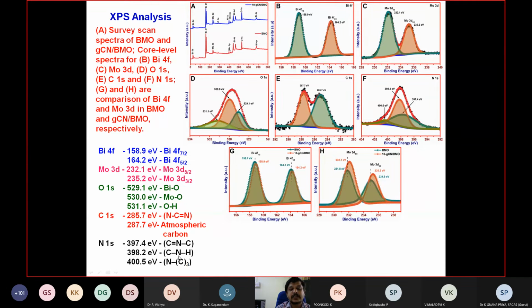Then the functionalities present in that nanohybrid material, over the graphitic carbon nitride, we have also confirmed through this XPS analysis. The formation of the heterojunction is also confirmed by the slight shift in the binding energy between bare bismuth molybdate and the nano heterojunction material. You can see there is a difference in the binding energy for bismuth and molybdenum in that nanohybrid material. That clearly confirms the formation of the heterojunction.